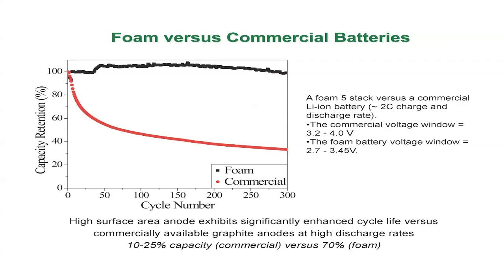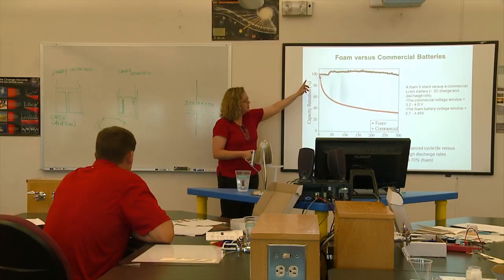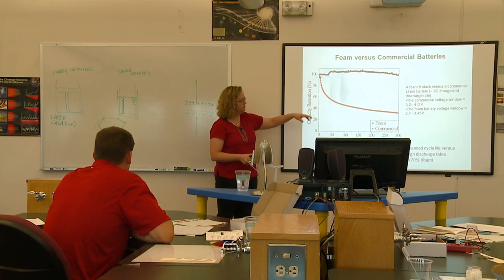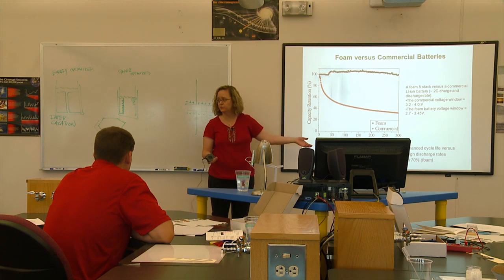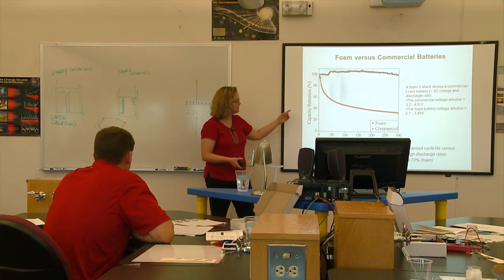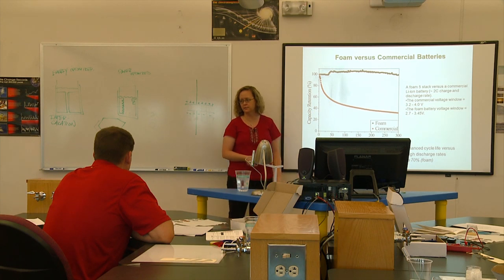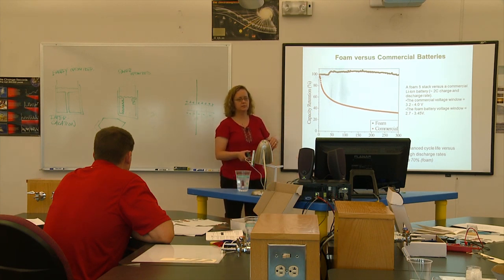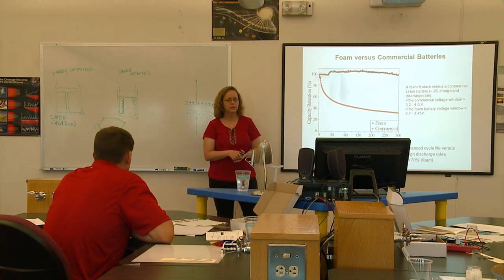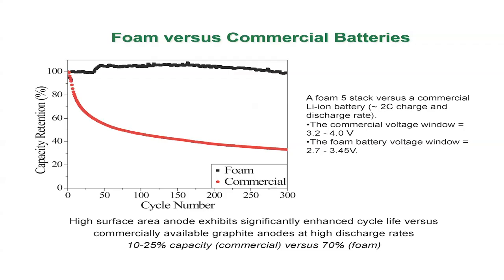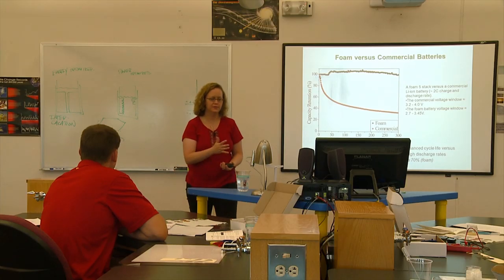So what we did is we took our battery again. Now, it's not the full 3D battery, it's just our anode. We took a normal battery out of a BlackBerry, actually. Stripped its controls off and cycled it the same way. And what I'm showing you in black is our battery, and in red is the BlackBerry battery. The voltages were different because the cathode materials were different. But what you can see is that a commercial battery is just not meant to cycle that fast for that many times. So its capacity drops pretty dramatically, whereas ours is still better. So the whole point is just that this whole idea of making electrodes higher surface area works. And that part is pretty obvious in this field.